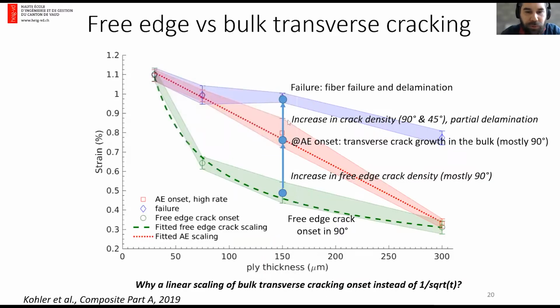So if we look at this graph, we can see that first we have these free edge cracks that appear. You have seen them in the video before. Then we have the acoustic emission onset with transverse cracking growth in the bulk of the laminate. And finally, we have an increase in crack density in the bulk, and then potential delamination, some limited delamination, and then fiber failure.